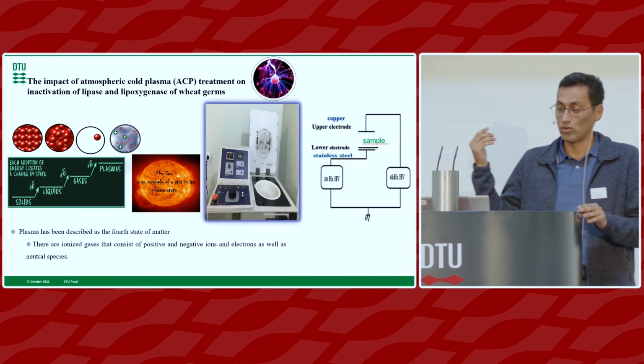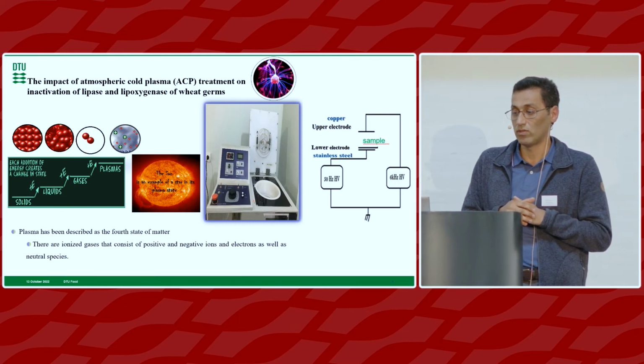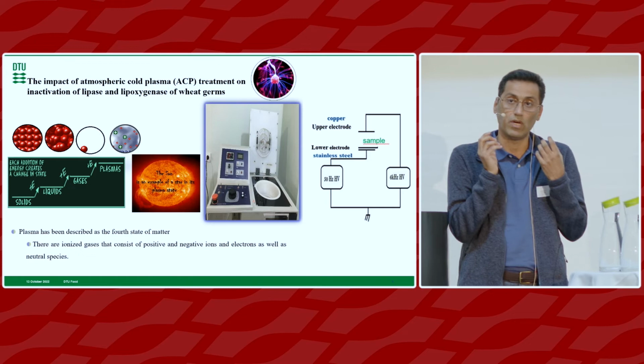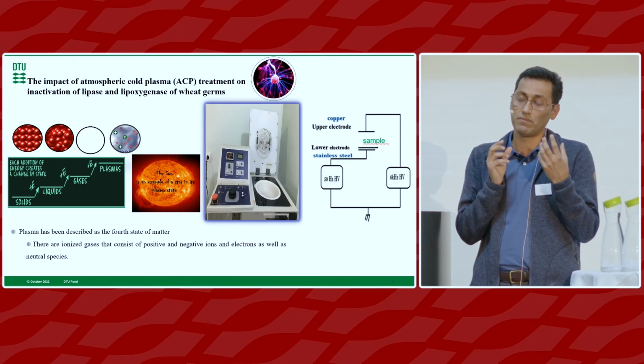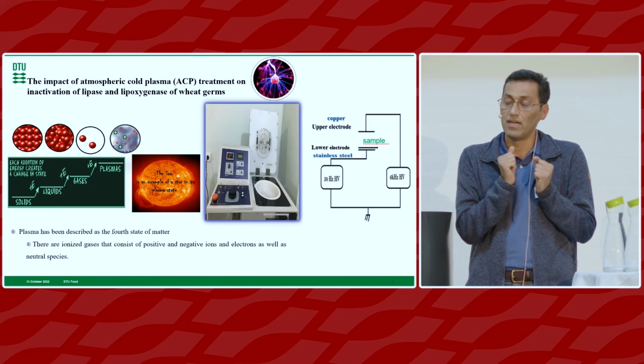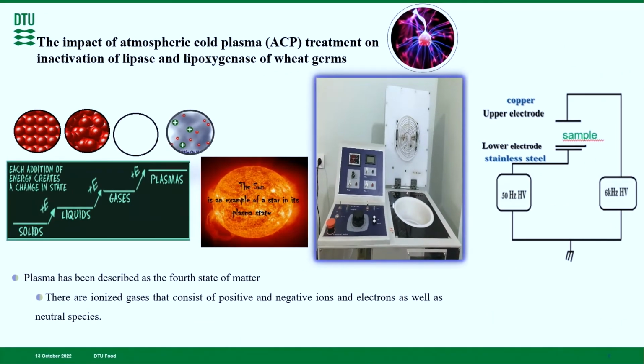The next step is to use high electric field. When you subject gases, different types of gases, air, nitrogen, oxygen, or argon, to high electric field, basically you are creating a wide range of reactive species like ozone, H2O2, ions, radicals. And then you can use this complex mixture to kill bacteria for surface decontamination, for instance.